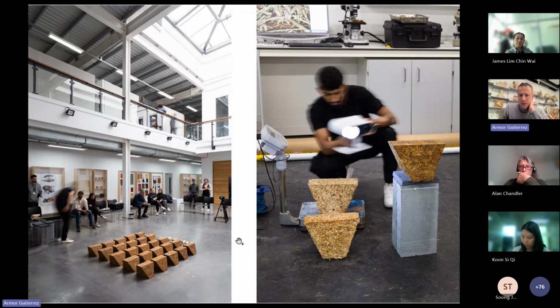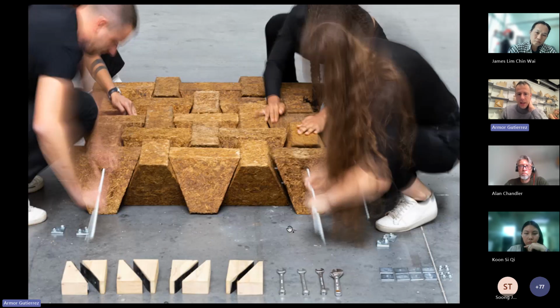We built it at the university using as well 3D scanning facilities to assess the shrinkage of the material. All materials that have curing process into them, they have different degrees of reduction when they cure. In our case, we were quite interested to see if there was any reduction depending on the fiber that we will use. So we tested with hemp, we tested with typha, we tested with sugarcane to see the reduction of each one of them. And then we compared it with the initial 3D model that we used to create the original pieces. And this is us setting it up together.